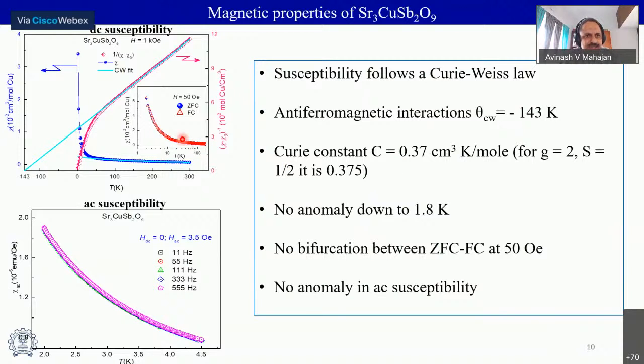Also, one verifies at low fields. One can verify at, say, 50 Oersted, and look for a zero field cooled variation in the susceptibility. So one typically expects, in the case of frozen moments or spin glass behavior, that you get a bifurcation in the susceptibility as a function of temperature for the ZFC and FC. So one gets some history dependence. So clearly that is not present here. One gets a total overlap of the data for ZFC and FC.